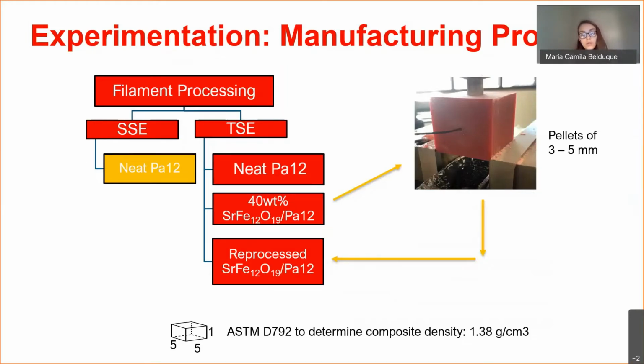Additionally, we followed the ASTM D792 to determine the density. We printed 5 by 5 by 1 centimeter cubes, where we found that they have a density of 1.38 grams per cubic centimeter.